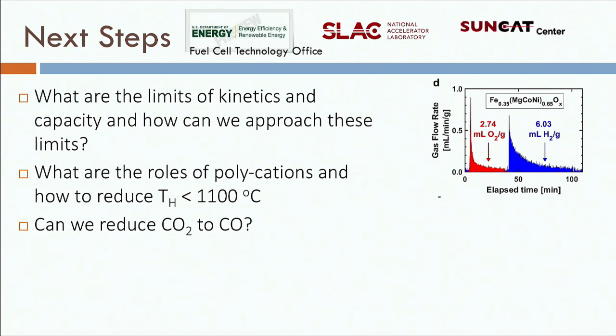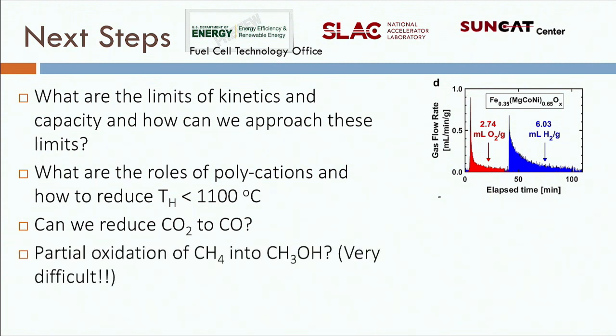We're also exploring, which is a very difficult reaction, whether you can do partial oxidation with this material. Because now you can mix and match various cations, and you can think statistically of copper atoms around the oxygen and maybe a zinc atom elsewhere, and then you can do the oxidation from the material itself to see if you can partially oxidize methane to form methanol. This is, of course, a very, very difficult experiment.